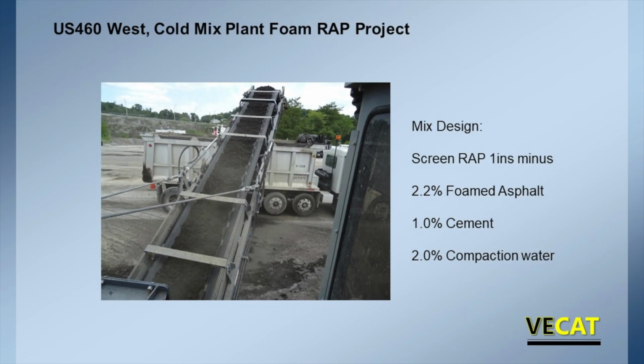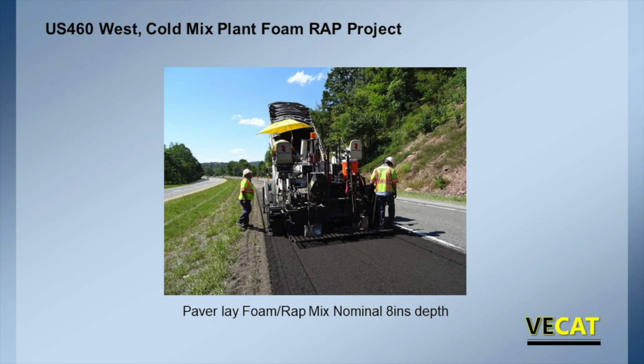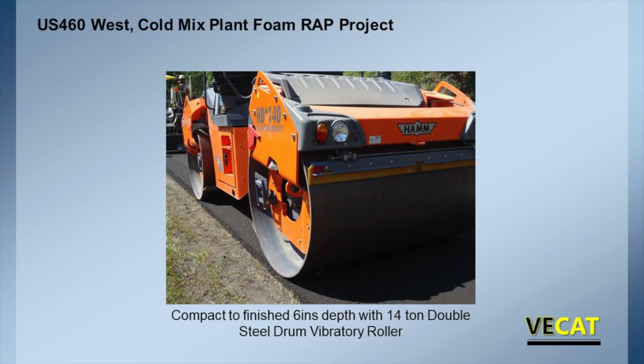This was screened RAP, 1 inch minus, 2.2% foamed asphalt, 1% cement, 2% compaction water. Similar deal, we used a regular strike-off screed. So here we're paving at 8 inches to get back to 6 after compaction. I usually work on roller size, a ton per centimeter, so 6 inches is 15 centimeters, so you want a 14, 15 ton roller. That's as a rule of thumb to get you good compaction with your recycled material. If you control your moisture, which you can do really well at the plant, there's no reason why you should not get really good compaction. I think you experienced that, Brian, yeah?